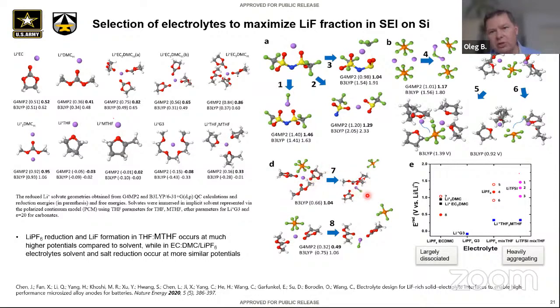Once we reduce them, there is LiF forming, and that has a reduction potential of about 1 volt, but this functional is known to overestimate. So it gets us to this range of reduction potentials for salt and solvent being the same, right? So if we use this type of electrolyte, we either have to be very, very slow to start initial decomposition due to the very small fraction of contact ion pairs, or HF, which is present. That's another process. But solvent is going to contribute, and if solvent contributes, they're going to be carbonates.